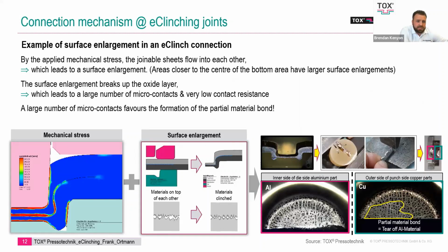So what you see here is a true example. And so you have, again, that high level of mechanical stress and that surface enlargement that is breaking up. You can see on the bottom right-hand side the breaking up of those oxides, and the stretching of that material, exposing raw parent material, where it's actually making excellent contact between raw parent, the lower material. In this case, it's aluminum and copper.